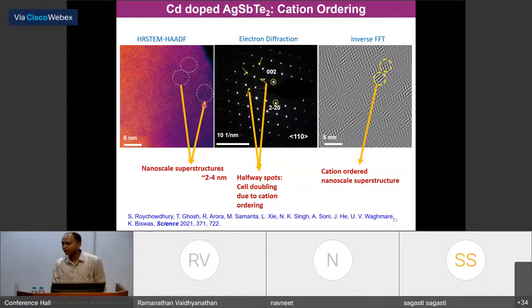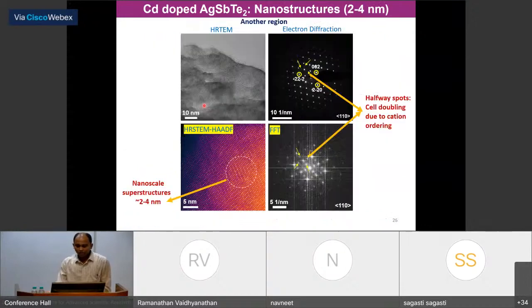And 2 to 4 nanometer is exactly the phonon mean free path size in AgSbTe2. So this can actually scatter the phonon as well. Then we have done more experiments, HRTEM experiments, where we see this nanostructure domain forming by cation ordering due to the cadmium doping. And here you can see clearly this nanoscale superstructure domain formation by atomic ordering.